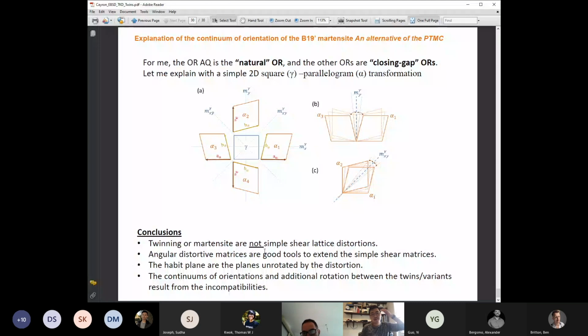Yeah. You see, in figure B, it's the continuum I need to put the B alpha vector in contact. This gives you a new orientation relationship, and this gives you a continuum of orientation relationships. And that's exactly what I could observe by EBSD and EBSD on nitinol alloys. But it's quite general, actually. It's the same thing in steels.